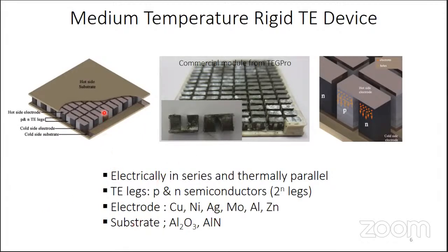Again, structurally, in the case of rigid thermoelectric material, all these things are normally put between two ceramic substrates, because ceramic is an electrical insulator and thermally conductive. That's why we put a ceramic substrate, and all these edges have to be reasonably sealed from the open atmosphere. You cannot leave it in the open atmosphere and heat it to 500 degrees Celsius, because everything will oxidize and crumble. So it has to be hermetically sealed. If it is less than 150 or 200 degrees Celsius, to some extent it's okay. You can pack it with something and then seal it with a polymer. This is how it is sealed here. You can see it's a commercial module. It is sealed with polymer.